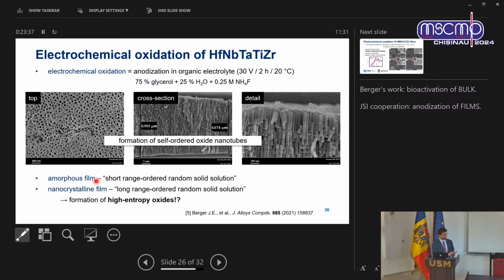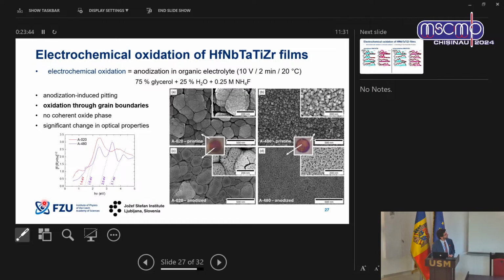So these are the results which were obtained by our Slovenian colleagues. On the left is the original amorphous film, on the right is the original nanocrystalline film, and this is the effect of electrochemical oxidation. You can see that it makes a similar morphology as was observed in the bulk studies.